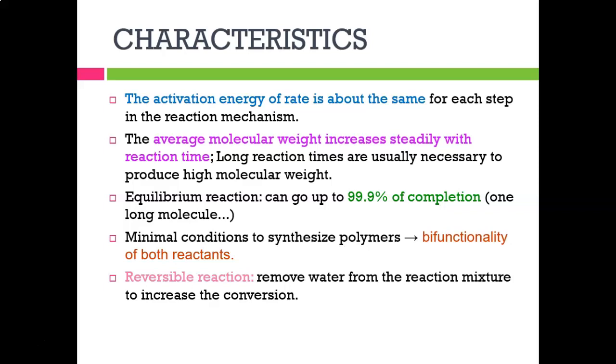Activation energy is the energy required to produce the reaction. The average molecular weight will increase steadily with the reaction time. Long reaction times are usually necessary to produce high molecular weight polymer, compared to chain growth, which requires less time. The equilibrium reaction can go up to 99.9% completion. A minimal condition to synthesize polymer is bifunctionality of both reactants, which means it must have two functional groups.